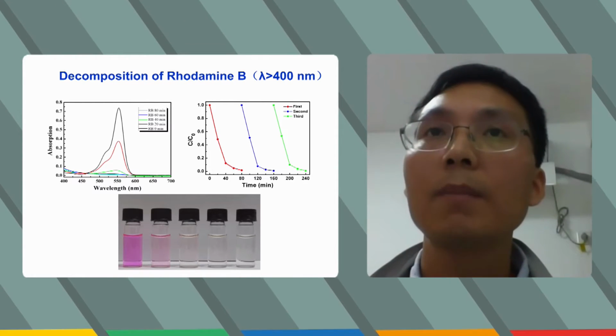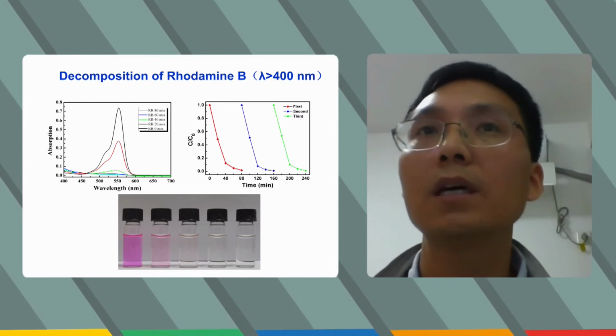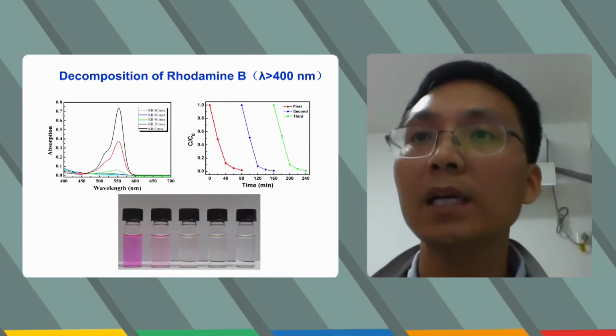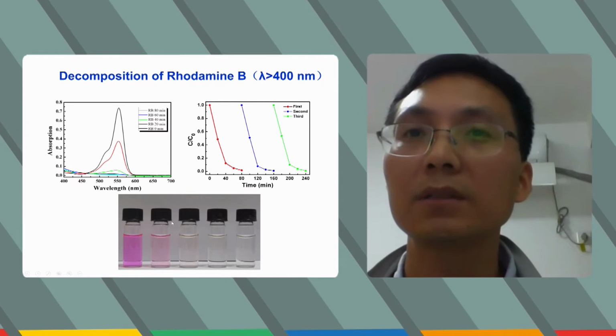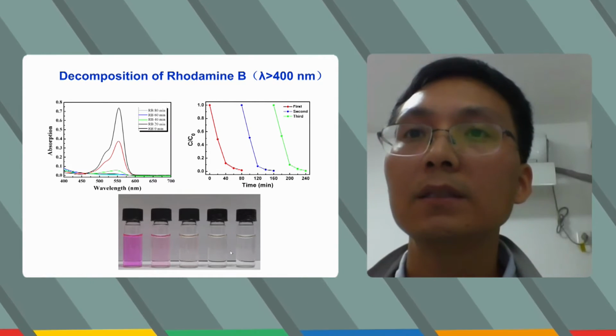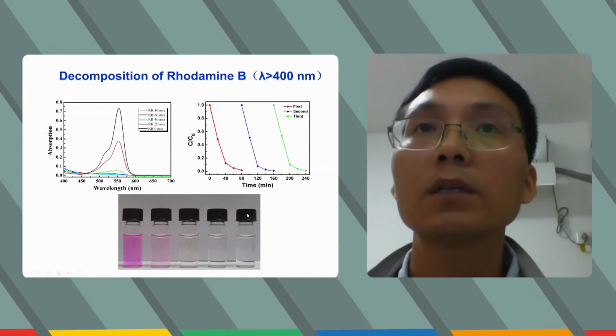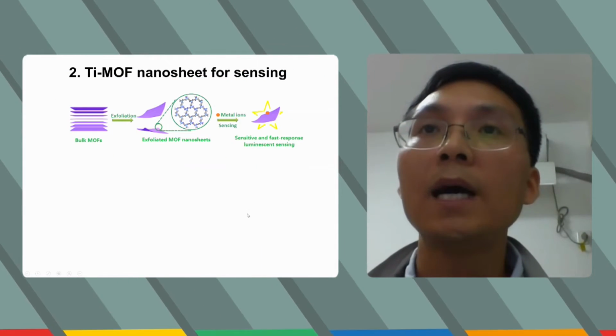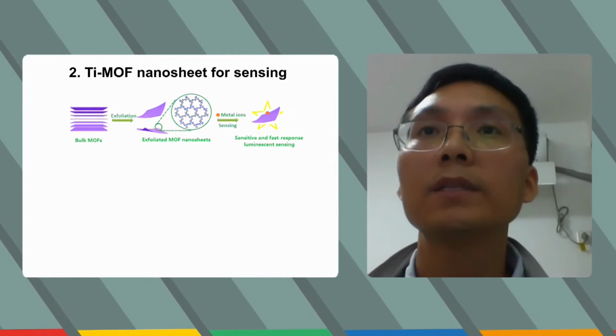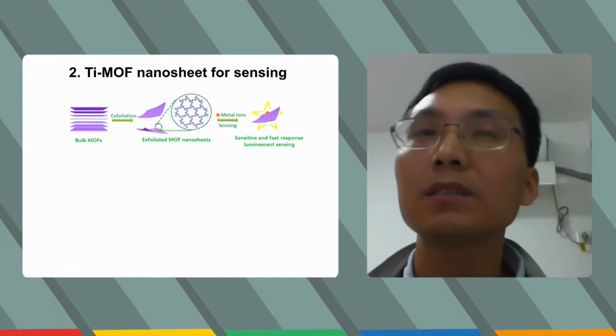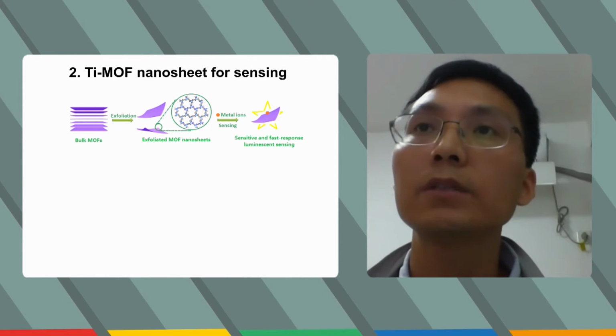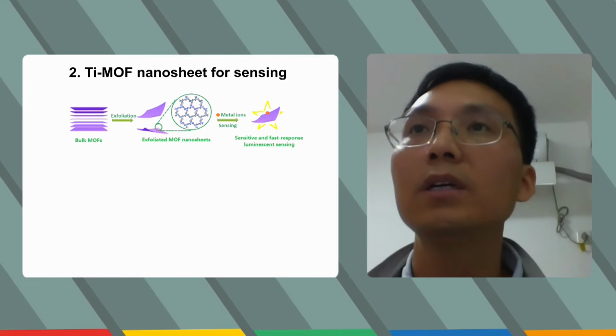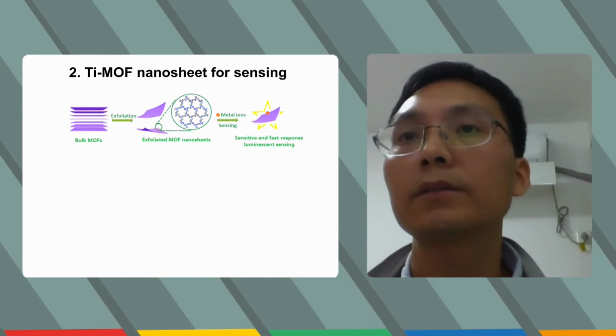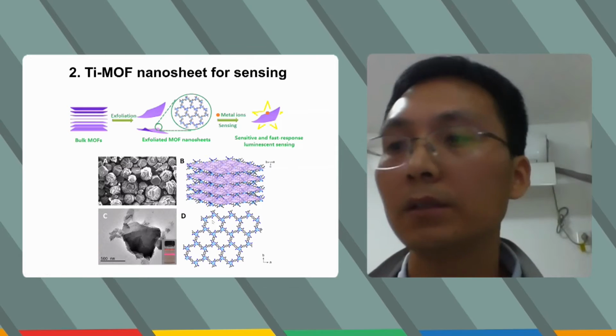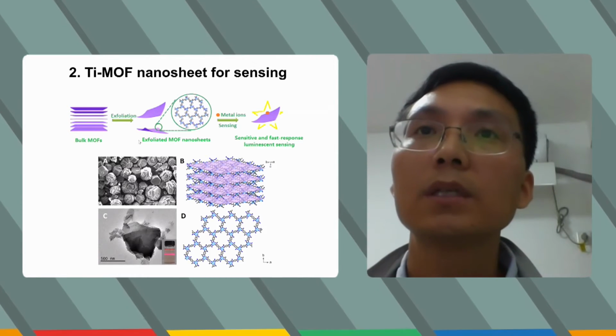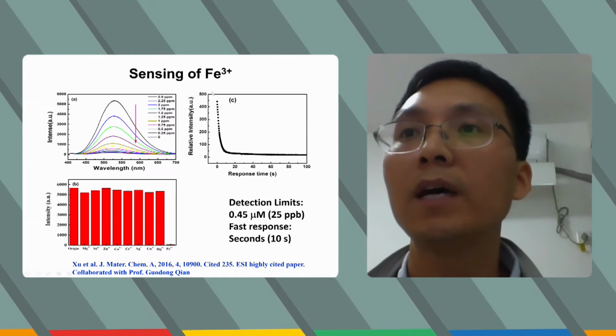It can be used for photocatalytic decomposition of organic dyes. We can see that after 10 minutes, the dyes are decomposed. Then we thought that since the MOF is layered, we could make some nanosheets. Also, this nanosheet can be very sensitive to ions. You can see that we got the nanosheets, and they can detect the ions very fast.